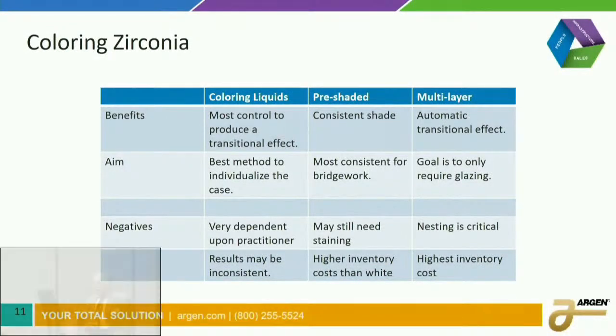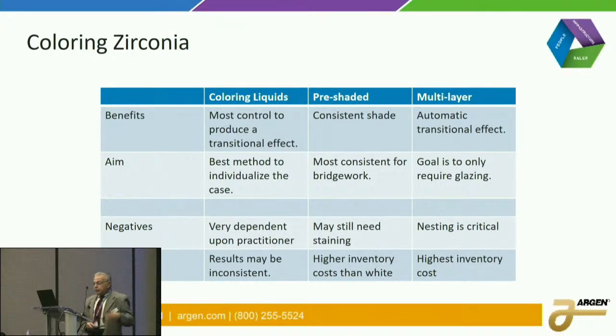Now, as the zirconia has changed in the marketplace, we changed the operation that you need to do in order to use it. First, we started off with the white material, which required you to use coloring liquids. Now, this gives you the most control to produce a transitional effect, and the aim is to individualize each case. The negatives, though, were very dependent upon the practitioner, and the results may be inconsistent. Now, we run into problems with this when you have, let's say, multiple single units for the same case, and you don't process them at the same time. You could get a different coloring result that may not be accepted by the dentist.